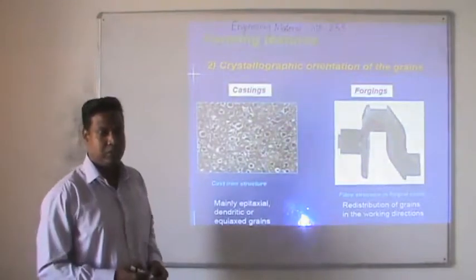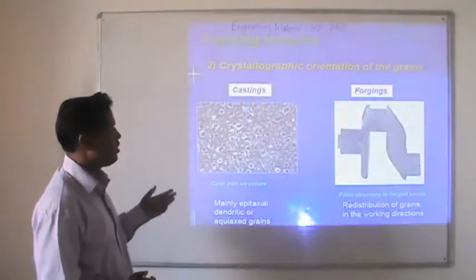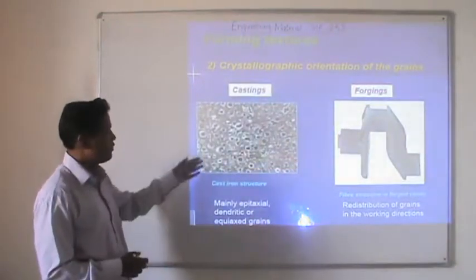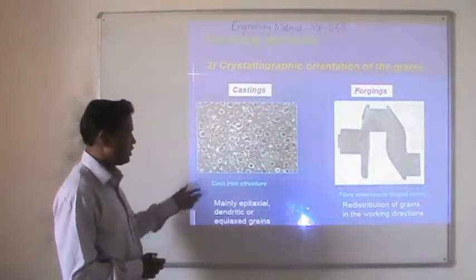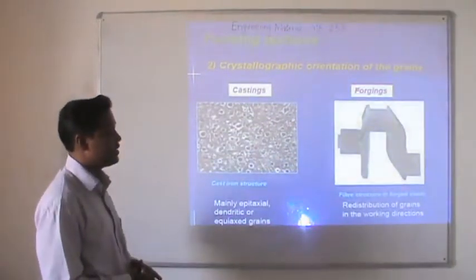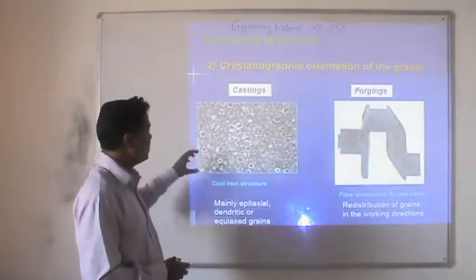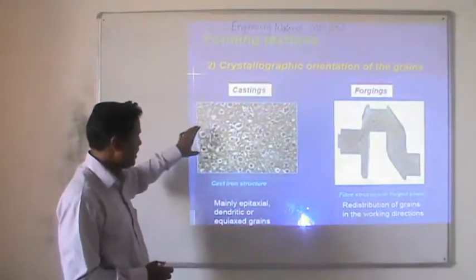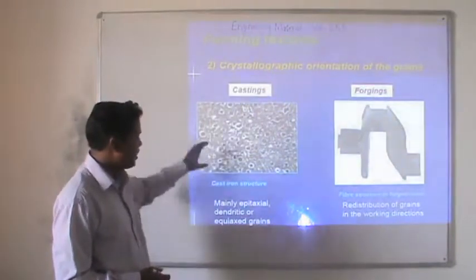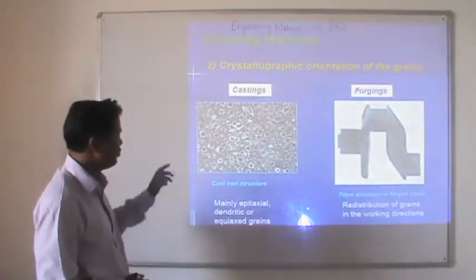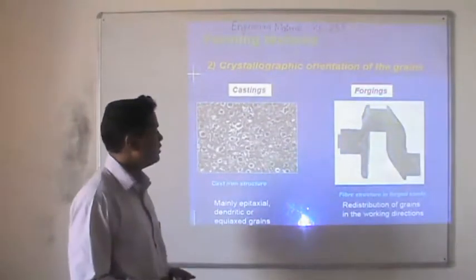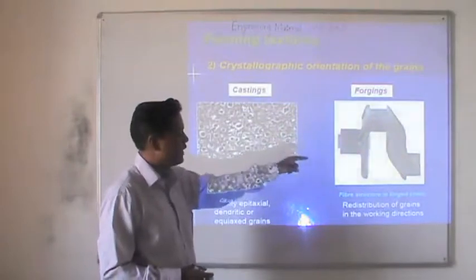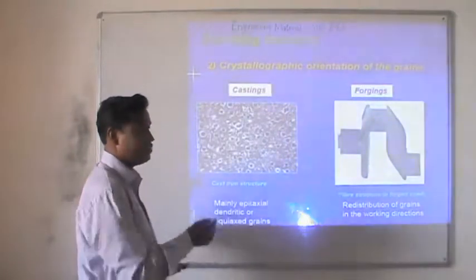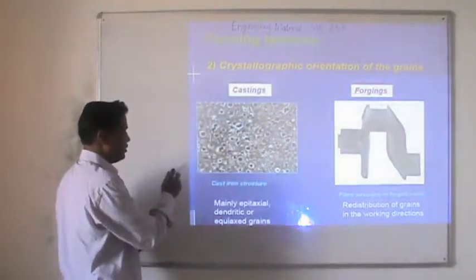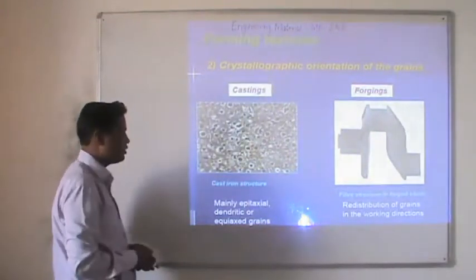Now the forming texture, this is the crystallographic orientation of the grain. In the first diagram, this is the cast iron structure, and in the second diagram, this is the fabricated structure in the forged steel. Here you see the grains, mainly the epitaxial and the dendrites of the equiaxed grains, and in the second, forging, there is redistribution of the grains in the working direction. This is the working direction, therefore the redistribution of the grains in that direction. And in this, these are the dendrites or the equiaxed grains.